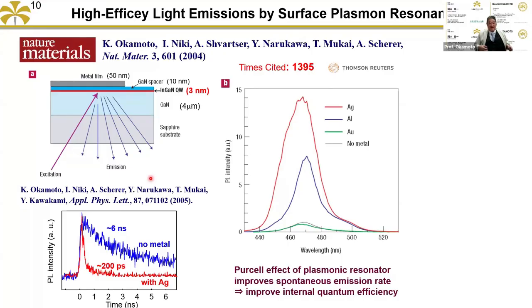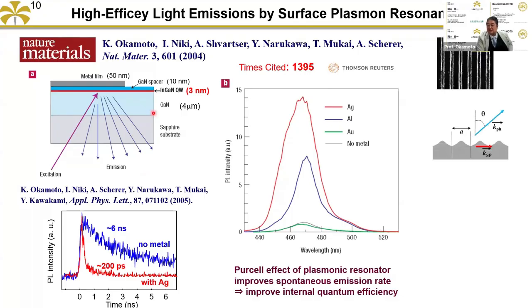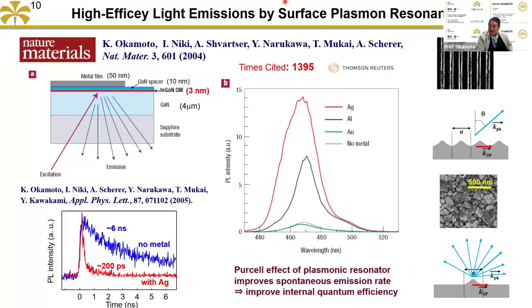And when I published this, I was asked, but there is no nanostructure. How can the surface plasmon couple to the light? Usually surface plasmon coupling needs a periodic grating or diffraction grating structure. But the good thing is that the metal evaporation gives some random nanograin structure. That grain size is almost similar to the wavelength of the surface plasmon polariton. That's why the direction becomes very broad, but the surface plasmon can couple to the light very easily.